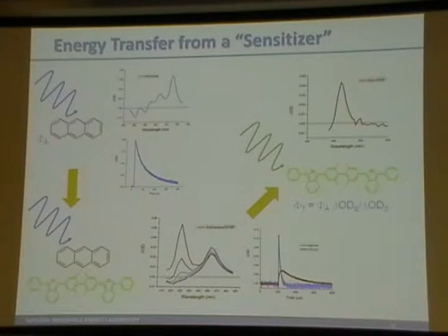The anthracene triplet gets shorter, and the diphenylisobenzofuran triplet rises, and of course it decays on some very long time scale. And then the final step in this process is to take away the sensitizer. Just put your molecule in solution and excite it directly, using essentially the same number of photons absorbed in both cases. And again, we see the same triplet peak, and we measure its amplitude relative to the final amplitude that